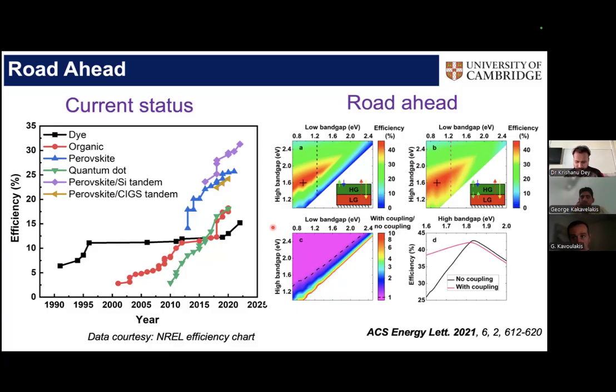Composition-wise, that's very important. The reason we chose FA cesium was because FA cesium based compositions generally have lower ion migration. If you have, let's say, a pure MA based composition or an FA MA based composition, they generally have more ion migration. So we wanted to start with a composition which is generally not that bad, which is why we chose FA cesium. Now, of course, you can ask why we chose 85%, 15%. It's primarily what gave us the best efficiency and best mobility.